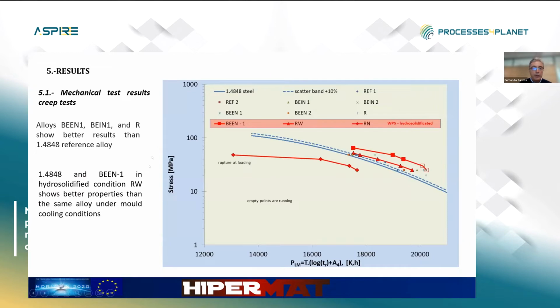If we go over the Larson-Miller graph that we have here, to concentrate on the main results, the lower line in red represents the natural cooling of one mold. In blue, you can see the standard values of this alloy, the 1.4848, and in red, the achievements that we have got by means of modifying the alloying. For example, the triangle line corresponds to a modification with water cooling. It improves significantly the values of the non-water cooling samples, and the square lines represent the new alloy enhanced with the water cooling. So we are achieving, in this logarithmic representation, significant improvements in creep for this alloy, not only changing the chemical composition, but also modifying the cooling rate. This is quite critical for us.